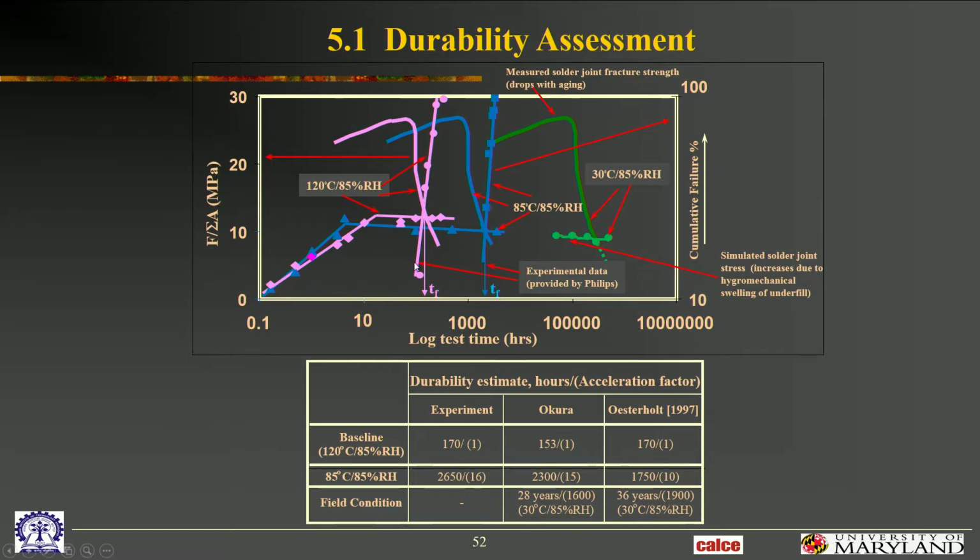Okay? And why is that happening? Because the underfills were not very good. The worst case filling was far worse than our best case filling specimens. There was a lot of piece-to-piece variability in the underfilling technology. So the end result of this was that the sponsor went back to the underfill manufacturer.